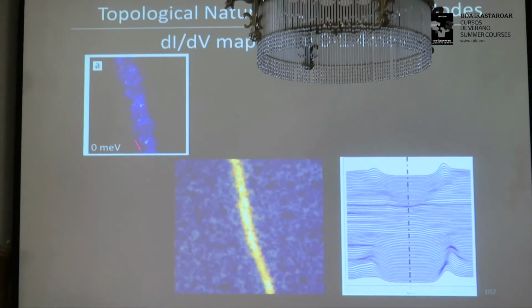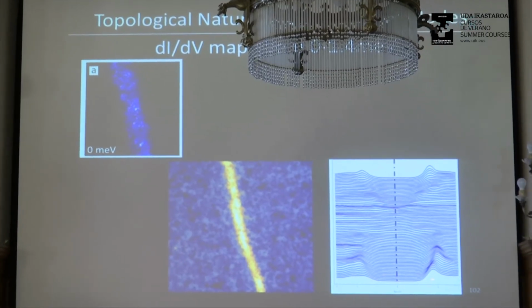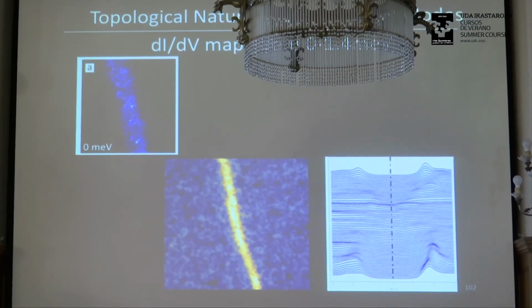Okay, so the last thing I want to show you, actually, I'm almost out of time, is one of the important things to show, if this is topologically non-trivial, is that this state must actually span the superconducting gap, right? So in fact, let me show you that. So right at 0 energy, this is a dI/dV map, right? So if you take a dI/dV map at 0 energy, you find a mode that's basically sitting right on top of this domain wall, right? So it's sort of localized to the domain wall.